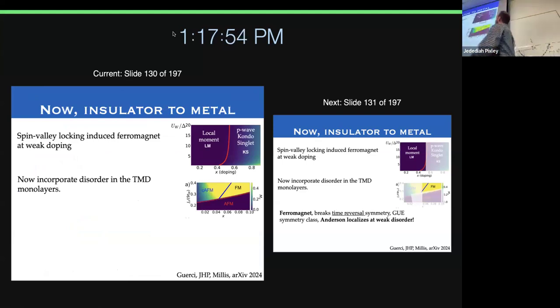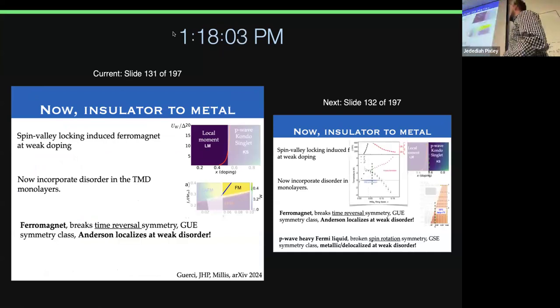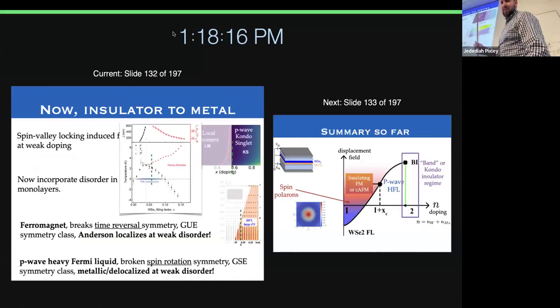So I have a spin valley locking induced ferromagnet at weak doping. I'm going to put in disorder. I'm going to argue as follows. So the ferromagnet, if I had disorder, I have broken time reversal symmetry. This is the so-called Gaussian unitary ensemble. And disorder is a relevant perturbation, and I will localize with infinitesimal disorder. What's cool about the P wave Kondo coupling is there's no broken time reversal, but there's broken spin rotation symmetry. So you're in the Gaussian symplectic ensemble, which allows a delocalized phase in 2 dimensions.